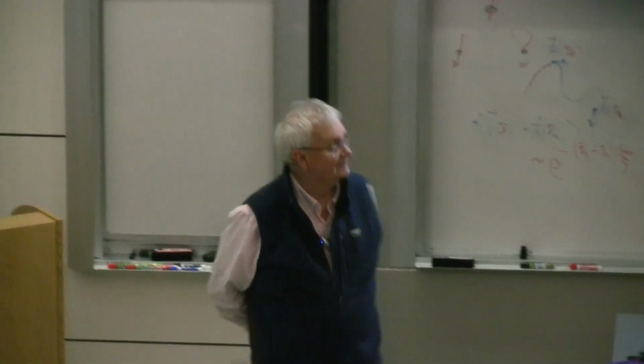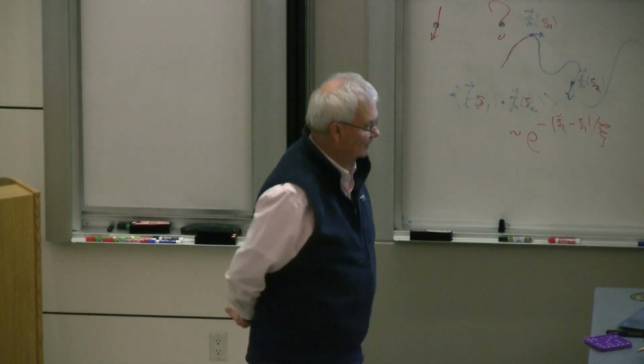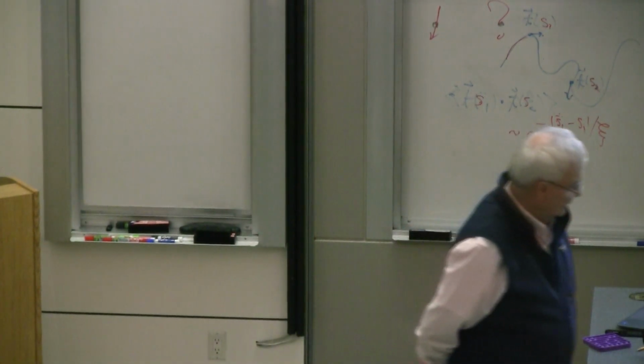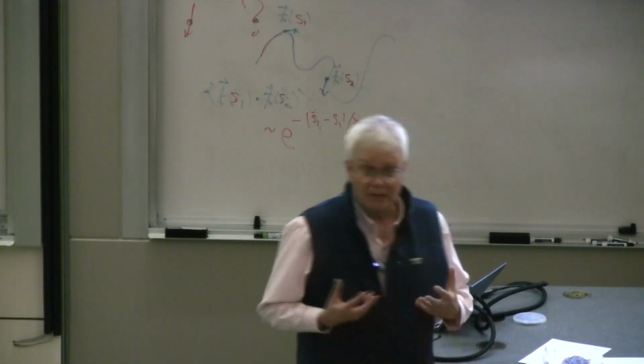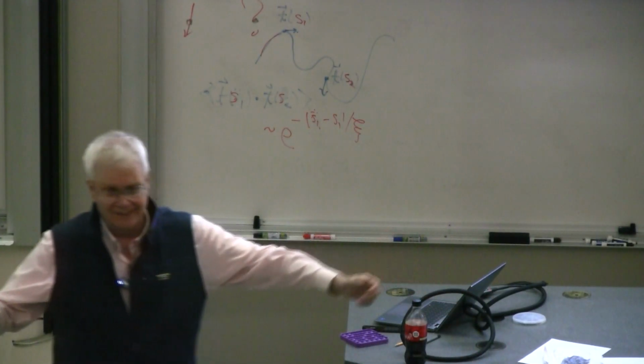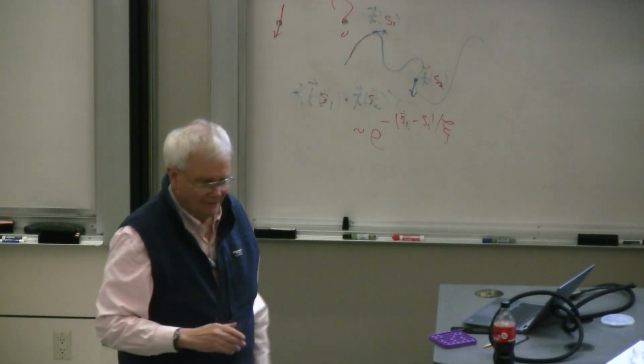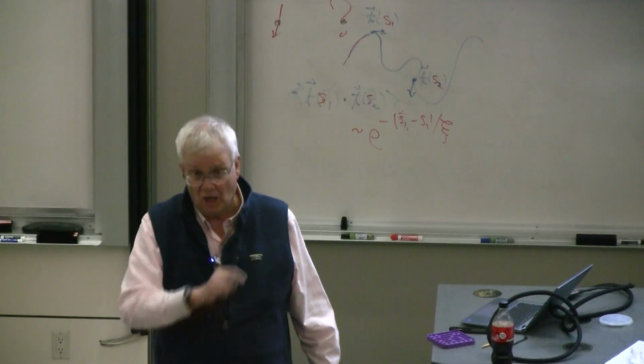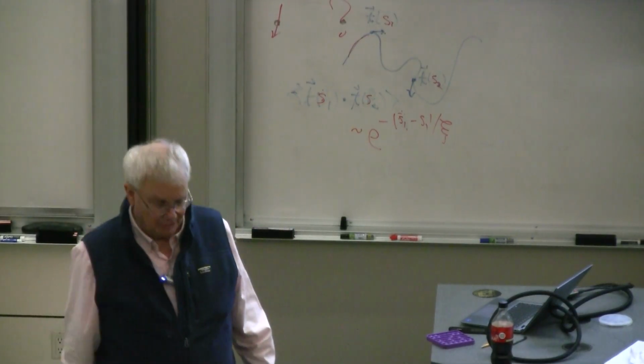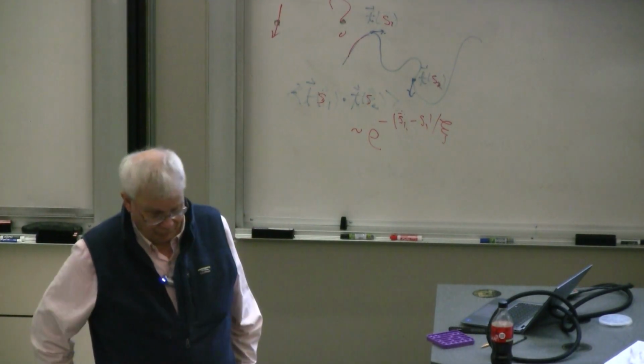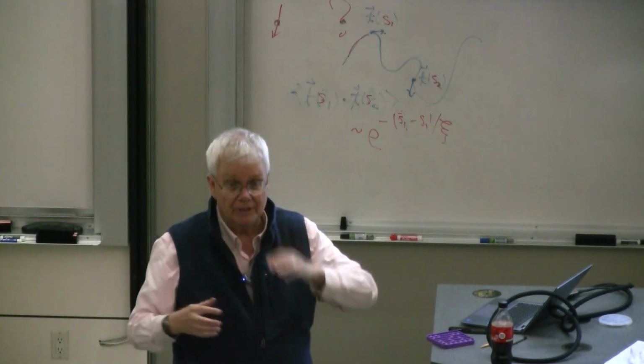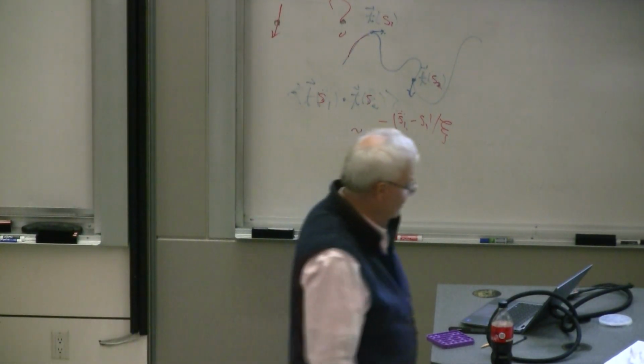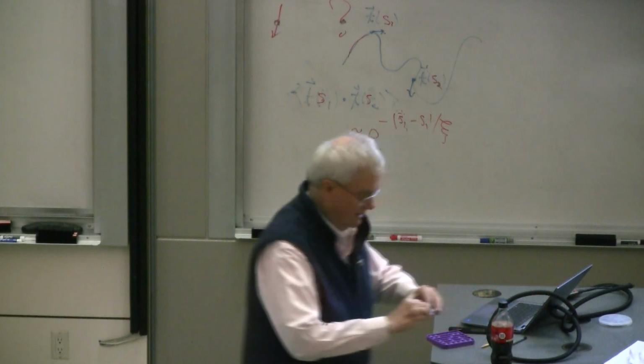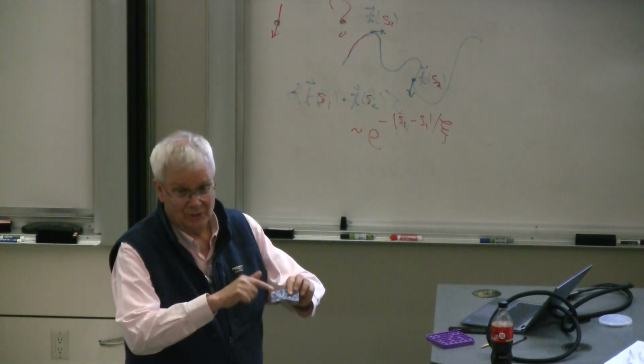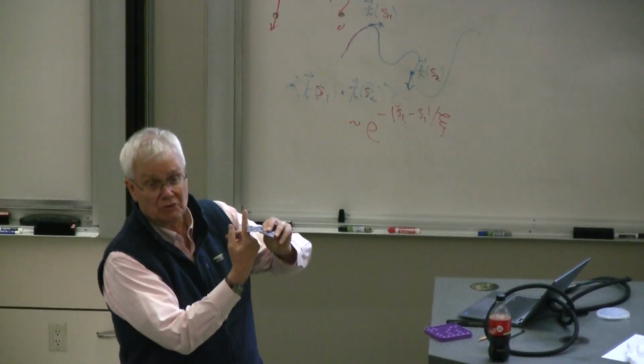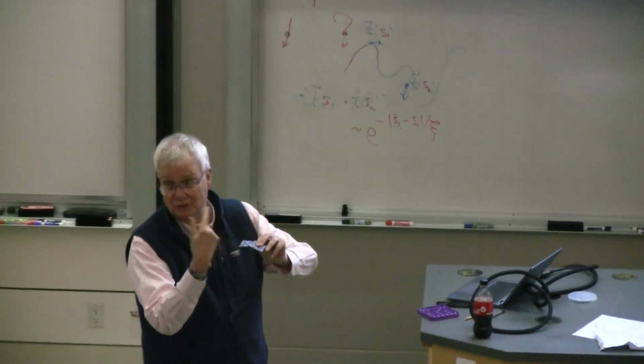This observation of the breakdown of self-averaging I thought was quite interesting. Is there an intuitive reason why? Well, the experimental evidence is very compelling. They make 30 of these things, line up all 30 of them, and plot the bending rigidity. It's always large, about 25 times bigger than a polished, beautiful, flat thing. But they're scattered, and then you make them bigger, and they scatter more. So I would say when the fluctuations in the height that you get from that 1 over q squared is comparable to the thickness, that's when the self-averaging breaks down.